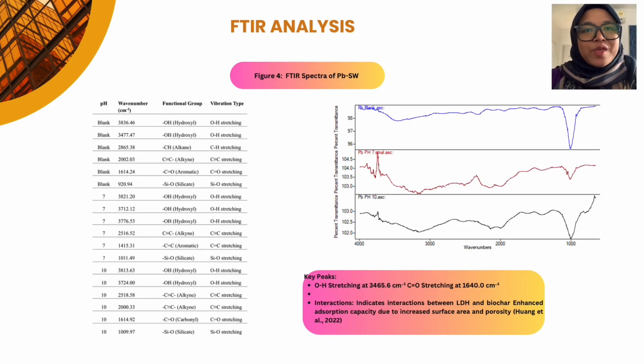Okay, let us review the FTIR spectra of the lead SW samples. For the lead SW sample, the hydroxyl stretching peaks were observed at 3,836.46 and carbonyl groups at 1,614.24. At pH 7, additional hydroxyl peaks around 3,712.12 were seen in the spectra. At pH 10, the silicate groups were noted at 1,009.97 and there was an additional peak for alkyne groups at 2,000.33. This shift suggests an effective interaction between lead ions and the composite material itself.